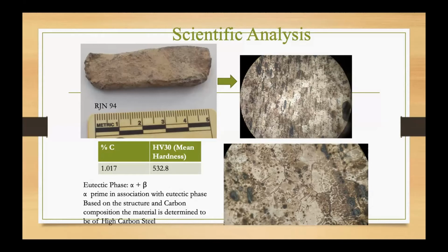Because an object which is used for cutting or chopping or maybe even butchering needs to be hard. It cannot be done with a soft metal. As you can see here, we have the eutectic phase, which is alpha plus beta. Alpha is basically the prime ferrite, which is in association with the eutectic phase. Based on this granular structure and the carbon composition of the material, it is determined that it is high carbon steel. You can see very prominent grain phases. Here the border lines are very clear. The black border lines are basically the carbon which is settled along the grain boundaries, and you have a proper pearlitic formation. This microstructure is basically a pearlitic formation.